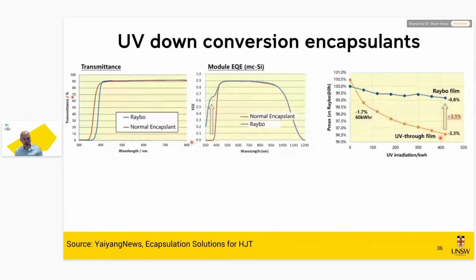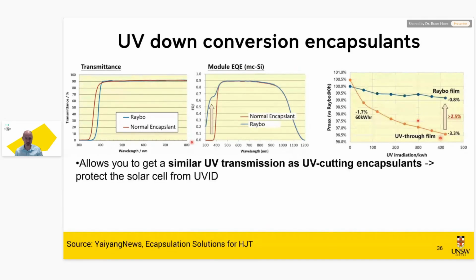And this is shown here. This presentation I could find on, probably that's a typo, but the Tanyang News, they did recently, where they show that the Raybo product has the transmission properties of UV blocking encapsulants, but the EQE properties of UV transparent foil. And these are results that I believe were on TOPCon, and they showed that the modules were more stable.